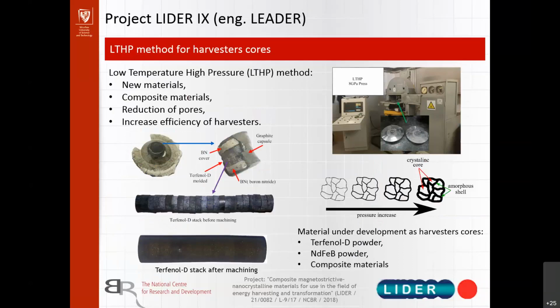We already made some preliminary tests with Terfenol-D material and the powder of Terfenol-D. So here are the results. As you can see, we obtained tablets of Terfenol-D powder, and then we stuck everything together and obtained such a, let's say, rod. But as you can see here, it was very narrow and not very centralized and so on. So we decided to make it better for experiments.